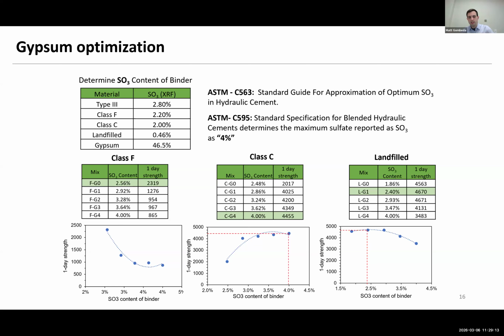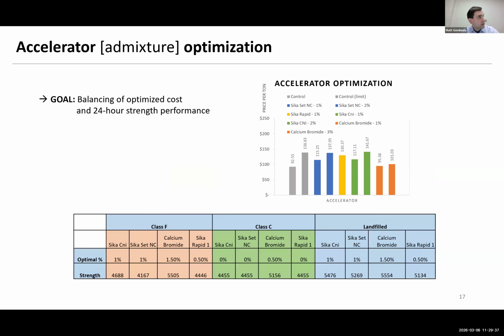So this process basically looks at different trials of gypsum dosages and finding where the peak compressive strength lies with regard to how much SO3 content is added into the binder. And you can see for the different types of fly ash there, we were able to determine what that optimum value of SO3 was. We also then did another study on accelerator optimization, used a few different products, and then basically narrowed down the dosages of those to, again, help to inform the effect on strength gain.